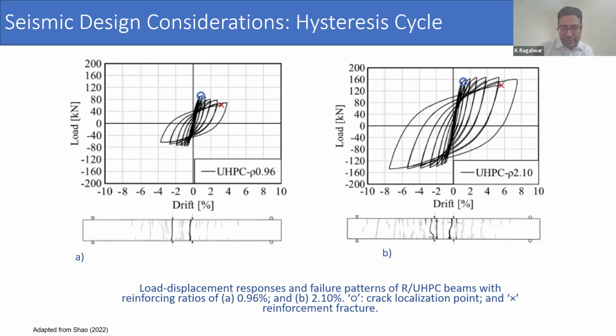So as we talked about, there is an inherently stronger bond between steel and concrete due to the high strength concrete. This stronger bonding comes from HPFRCC's ability to restrain splitting cracks as well. In other words, the matrix grips the steel bar more tightly, resisting crack propagation around the reinforcement. While this is generally beneficial for load transfer and bond strength, it also means that when a localized crack is formed, the plastic deformation of the reinforcement gets confined to a very short region near that crack. As a result, the strain in the steel accumulates quickly in that small zone. This localized concentration of plasticity leads to sharper curvature, faster strain accumulation, and ultimately, possibly, early bar fracture as well.